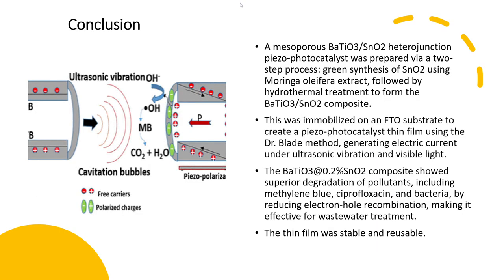So in conclusion, the barium titanate at 0.2% tin dioxide heterojunction piezo-photocatalyst demonstrated significant potential for the degradation of a wide range of pollutants, including dyes, pharmaceuticals, and bacteria, making it a promising solution for wastewater treatment. This study highlights the efficiency of the piezo-photocatalyst in reducing electron-hole recombination, enhancing photocatalytic performance, and providing a stable, reusable thin film. The successful collaboration and funding support from various institutions contributed to the advance of this research, paving the way for further innovations in environmental remediation technologies.